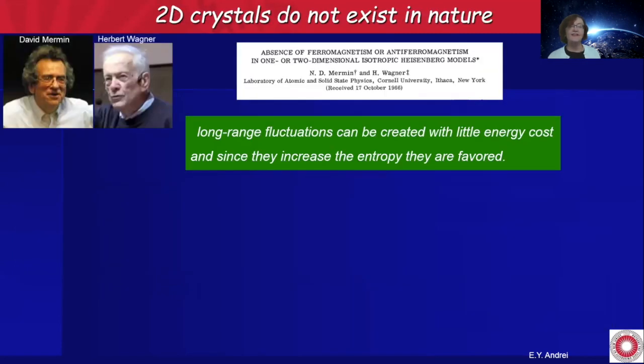Now, this is actually quite surprising in view of this paper here. This was a very influential paper by David Mermin and Herbert Wagner in the 60s that argued that long-range fluctuations can be important in a two-dimensional or one-dimensional material. Fluctuations are very cheap energetically, and as a result, they are favored because they increase the entropy. So as a result, what they argued, or they seem to have argued, is that there's really no long-range order in dimensions less than 3, and in particular,